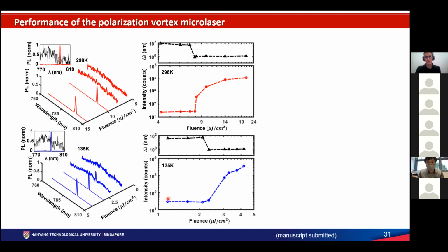At lower temperature, we see again only one single lasing mode. Now the threshold is lower, almost 1 order of magnitude lower, about 8 times lower. And the line width also collapses there. So the line width is almost sub-nanometer. So we know we're in the lasing regime.